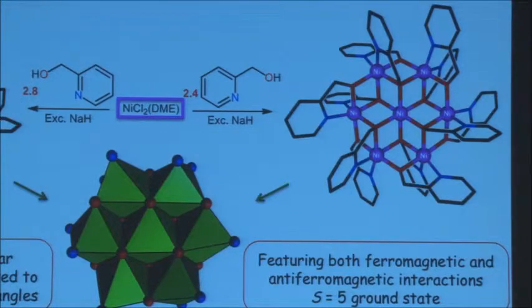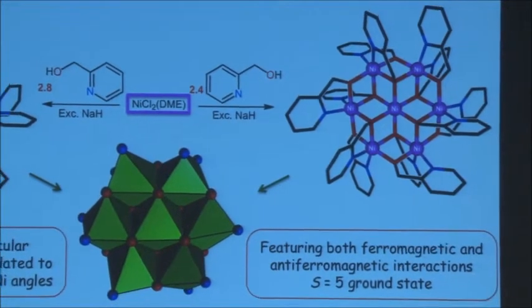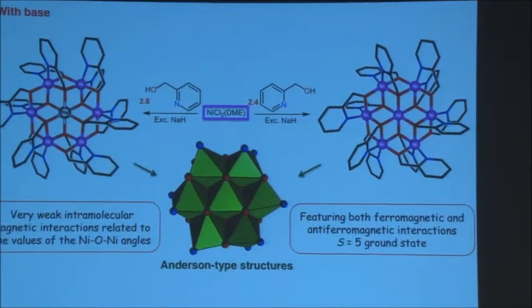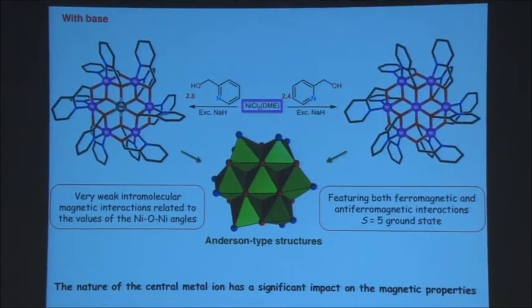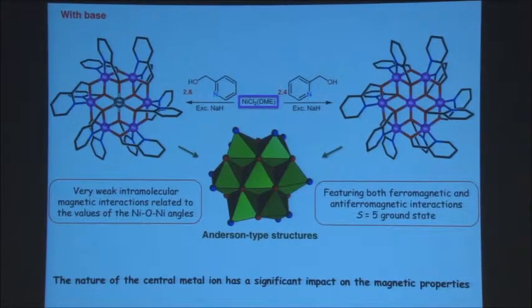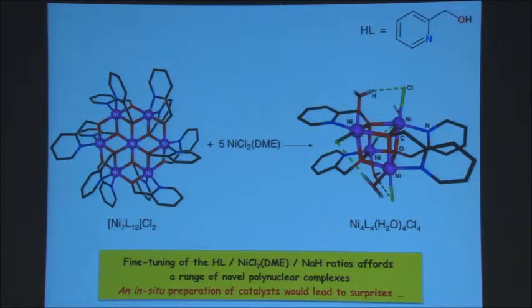So really, you can see that this nature of the central ion here has a strong impact on catalysis. I don't want to go into the details, but also on the physical property that is here molecular magnetism. And you can go on and now try to see whether you can convert one structure into another. So for example, we took the wheel structure here that will react with more nickel in order to decrease the ligand-to-metal ratio to go to 1. And indeed, you can form the cubane.